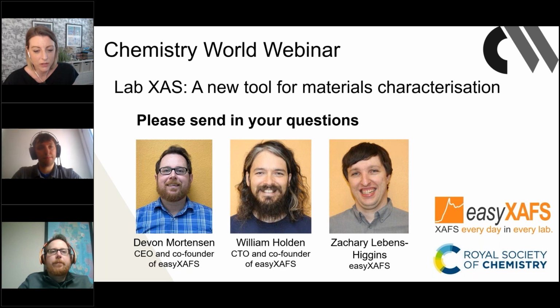Right. The next question I'll move on to is really useful, actually. What are the concentration limits of the system? It's probably a bigger question than it sounds, though. Yeah, there's a lot that goes into this. Of course, it depends on what your element is and what matrix your element is in. But in general, for transmission mode, it's typically on the order of weight percent, particularly for those 3D transition metal systems. As you switch to fluorescence mode, you can push the limits of the system and go on the order of a sub-weight percent. For example, for thin film samples, we've tested down to 50 nanometers, and that's relatively dilute. And also in carbon matrices, often on the order of 1,000 ppm or less. Okay, thank you. That's been good.